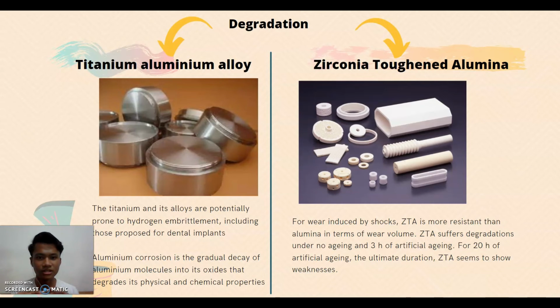The last material is zirconia toughened alumina, or ZTA. For wear induced by shocks, ZTA is more resistant than alumina in terms of wear volume. ZTA suffers degradation under no aging and 3 hours of artificial aging. For 20 hours of artificial aging, the ultimate duration, ZTA seems to show weakness.